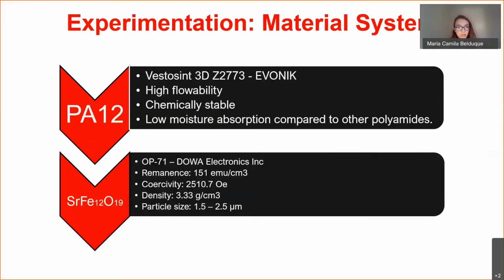As filler, we're going to use strontium ferrite, OP71 from Dowa Electronics. It has a remanence of 151 emu per cubic centimeter, a coercivity value of 2,510 Oersted, a density of 3.33 grams per cubic centimeter, and a particle size of around 1.5 to 2.5 microns provided by the manufacturer. This material, the strontium ferrite, is a ceramic hard magnetic ferrite with a hexagonal structure and significant magnetic crystalline anisotropy.